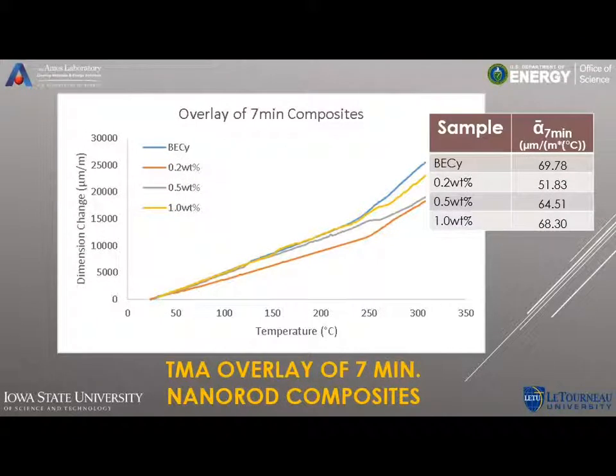For the 7-minute nanorod composites, you've got clearer lines here. And for the pure polymer, there is a coefficient of thermal expansion at 69.78. For the 0.2wt%, it's 51.83. So it's dropped down a good 17 units for the coefficient of thermal expansion. And then the 0.5 and the 1.0 show lesser drops for the composites. And so again, we're seeing that the 0.2wt% is showing distinct change from the pure polymer.